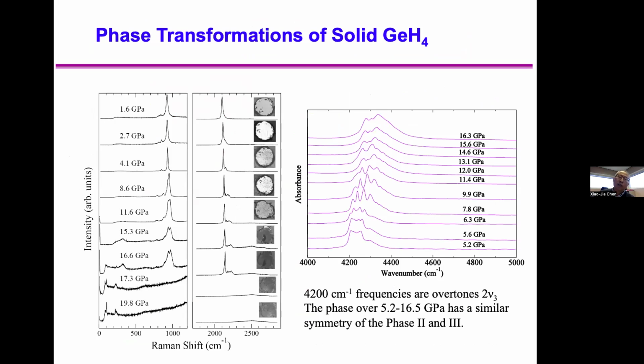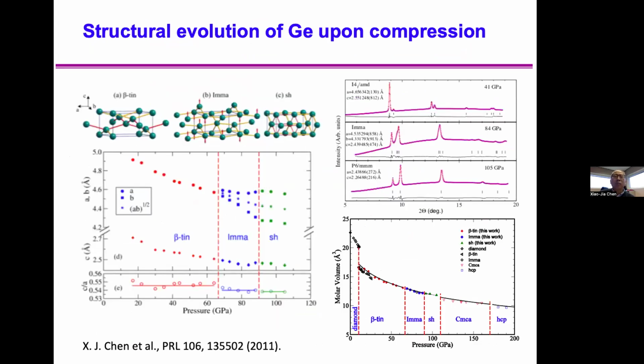Also, we worked on germane. You can see the phase transformation in this system. We can see systematic changes either from Raman or from the infrared spectrum. At that time, we saw there's a dissociation of silane and germane at high pressure. If that happened, that's germanium, and we are in a hydrogen environment. That's why we mentioned germanium will be surrounded by a very good hydrostatic pressure medium.